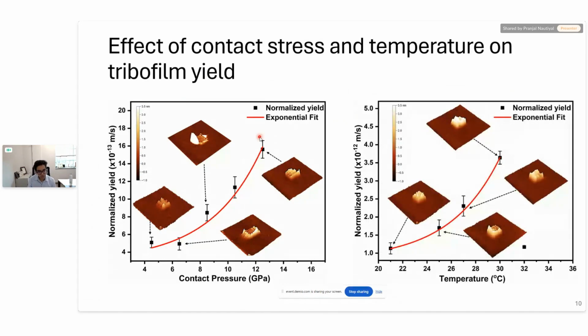We also studied the effect of temperature on tribofilm formation. And within a narrow window of 20 to 30 degrees Celsius, the temperature also promoted tribofilm growth. And we can clearly see an exponential increase in the yield of tribofilm as a function of temperature. When we increased temperatures beyond 30 degrees Celsius, we failed to observe this increase. And in fact, there was less tribofilm generated. And this can very well be understood by considering the desorption of hydrocarbon molecules at high temperatures. Because as we increase the temperature of the alloy, the hydrocarbons will tend to desorb and leave the surface. So that will undermine mechanochemical reactions, which is why we see a very narrow temperature window for growing tribofilms on this alloy.